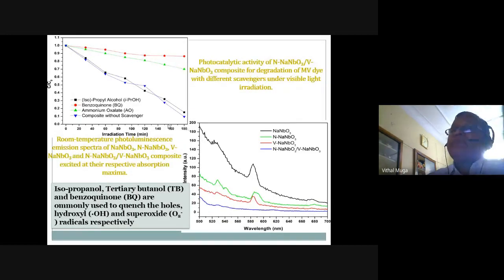Now, we have also used scavengers to identify the type of material. Isopropanol, tertiary butanol, and benzoquinone are commonly used to quench holes, hydroxyl radicals, and superoxide radicals respectively. That means if you do it in the presence of benzoquinone, then superoxide radicals will be scavenged. Once they are scavenged, then your photoactivity decreases. For example, you see the isopropyl alcohol.